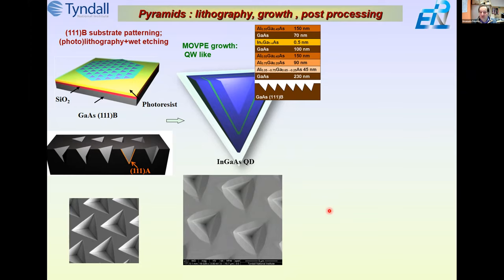But fundamentally, what happens is that here in the middle, the fast diffusing atoms, indium in this case, will concentrate there more than the gallium ones. And so we have an indium rich region, which is fundamentally thicker than anywhere else, there in the middle. You can call this capillarity, as other people have done in the past, or you call it that there are more bonds there. It doesn't matter in the end of the story. There is a higher growth rate in the middle, and that promotes the formation of a thicker layer because it's confined in three dimensions, then you get a quantum dot.